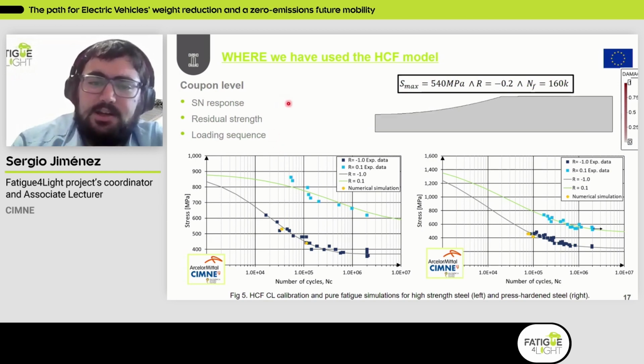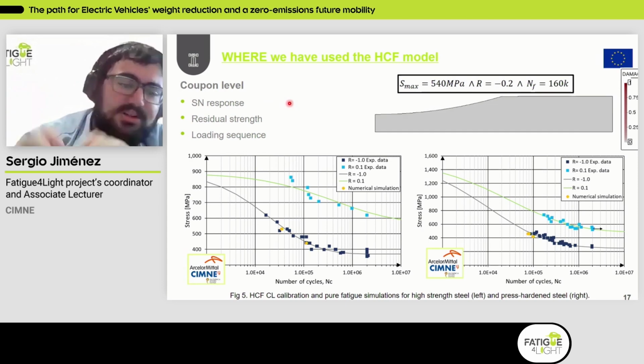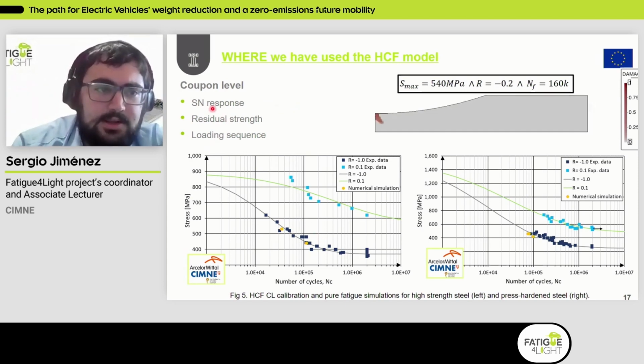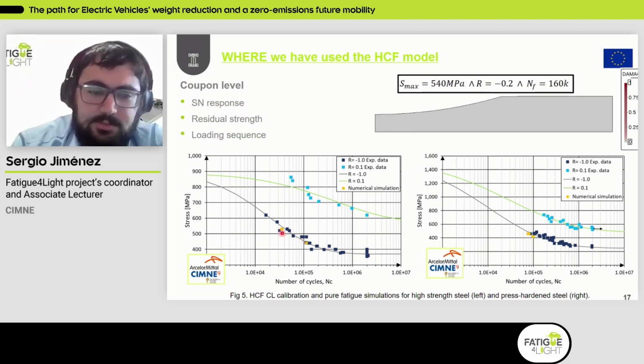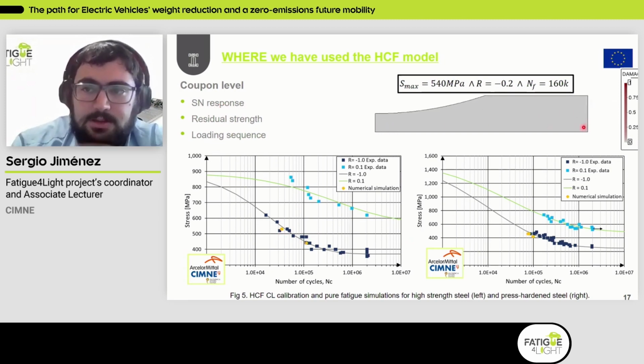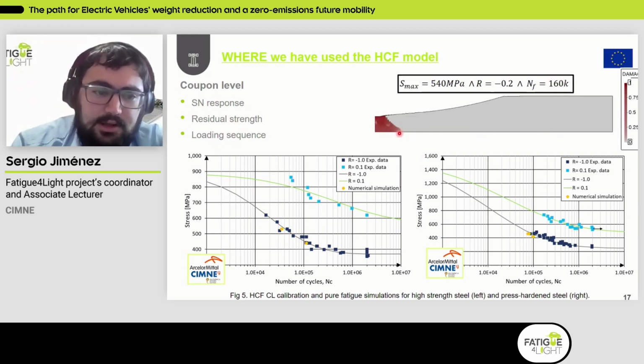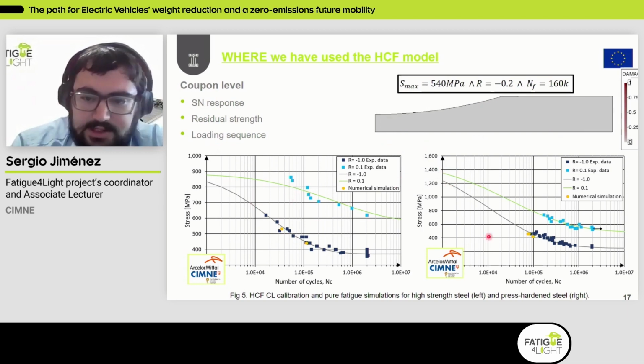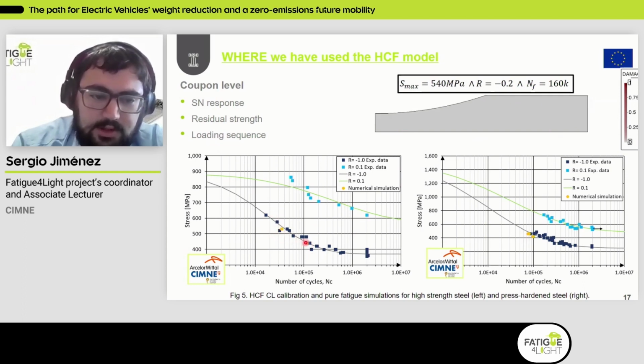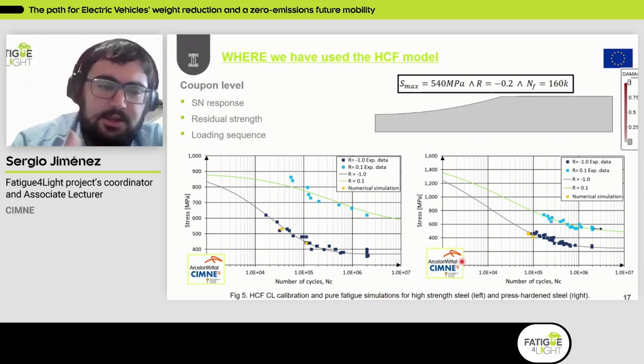But just considering that this is the small scale case examples, I've just included here this pure fatigue or SN response experiments, okay? So basically what we are doing is introducing cyclic load all along the life of the material, and at certain point damage starts propagating on the sample and it completely fails the geometry. And here you can see the comparison of some of the numerical simulations in yellow with respect to the dots which correspond to the experimental campaign. So we are in good agreement for these two, high strength steel and press hardened steel used in the Fatigue4Light project.